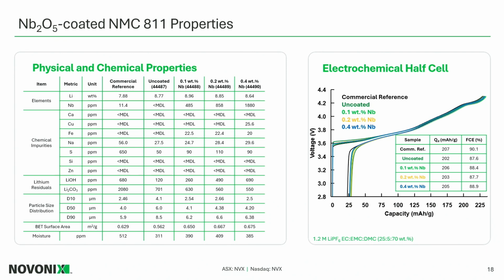On the right-hand side of the screen, I'm showing coin half-cell metrics for the commercial product in black, a control uncoated NMC811 that we synthesized in dark green, and then the series of other materials. The most remarkable thing I find out of these data is that with only a very small amount of niobium surface coating, you achieve a comparable first discharge capacity to the commercial reference powder, which is always good to see. And we'll return to that in the next slide.